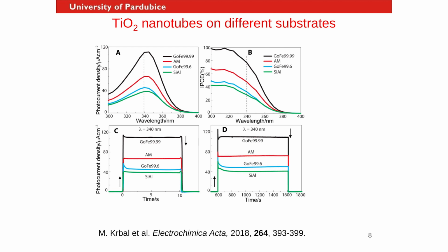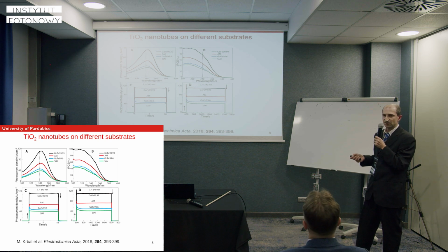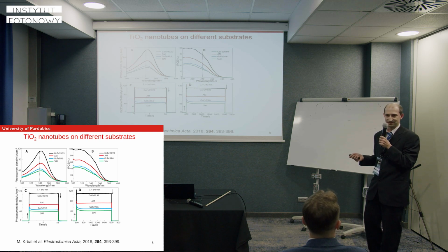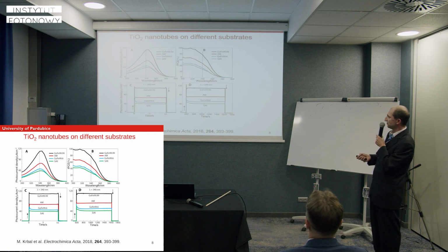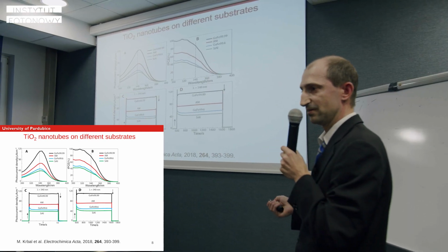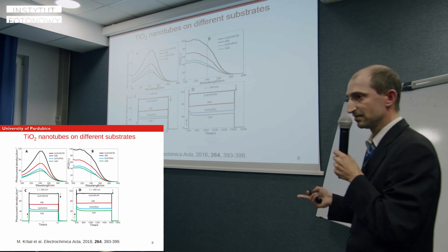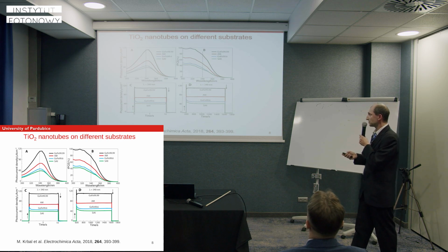And this is the result from the photocurrent measurement. What we found is that one of them was extremely efficient. We did it maybe 3 times, and this picture is always the same, actually. We didn't know what had happened, but here you can see that even if we expose it for maybe 1,000 seconds, which is the limit of the shutter of the spectrophotometer, there is no fading. So that means it's real and stable. And what is the origin of that?